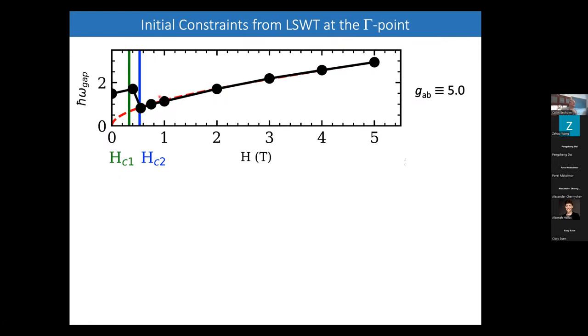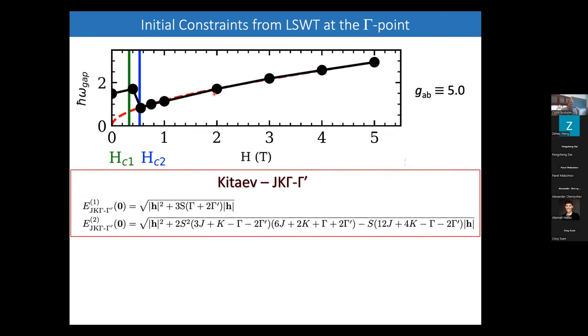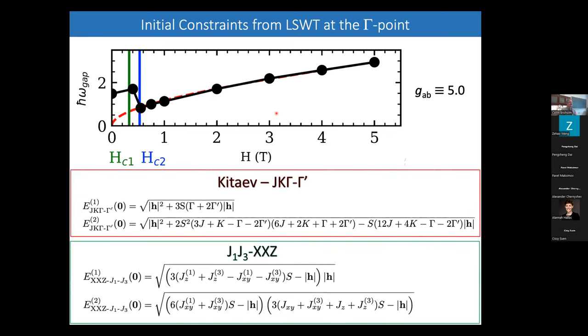And so this plot shows you the gap energy. So the lower energy gap is a function of applied magnetic field. We know separately from susceptibility measurements the in-plane g factor. And so it is possible to determine the field dependence of that gap for each of the two models that we're interested in, the Kitaev J, K, gamma, gamma prime and the J1, J3 model, so that these can be calculated in conventional spin wave, classical 1 over S spin wave theory. And you get these two expressions.